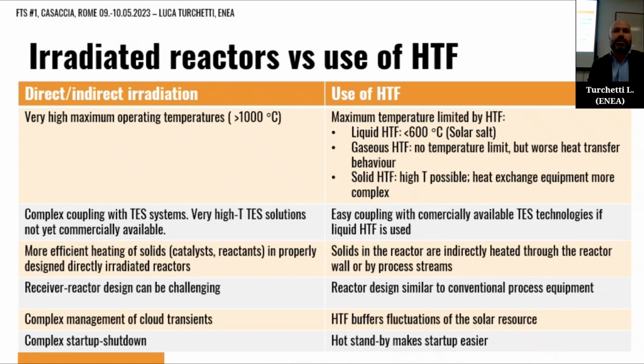So let's compare these two different approaches. All have pros and cons, of course. Let's start with the operating temperatures that we can achieve when you go for direct or indirect irradiation. With irradiated reactors, we can achieve very high temperatures, which are basically limited by your concentration systems and, of course, by the resistance and features of the materials that you're using. Current applications, which are not industrial but research applications, high TRL but still research, can achieve even temperatures above 1000 degrees Celsius.